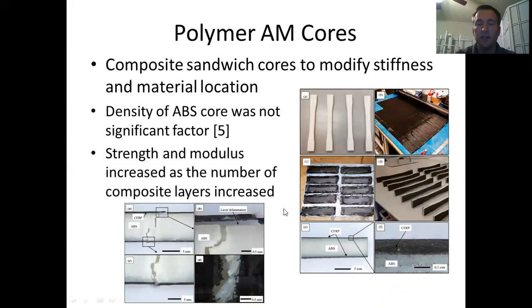And the last approach or design consideration is having polymer additive manufactured cores inside of your composite sandwich. And this adds stiffness, and you can also control where the material is within the core. So a couple of studies were done on this, and one used ABS cores, and they found that the density of the cores didn't have a significant effect on the strength and modulus of the part, but the number of layers of composite material that they applied to the outside did. So this picture on the right shows the process of building it up, and then here is a picture of the fracture of it.